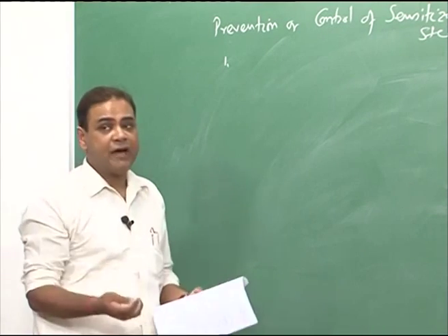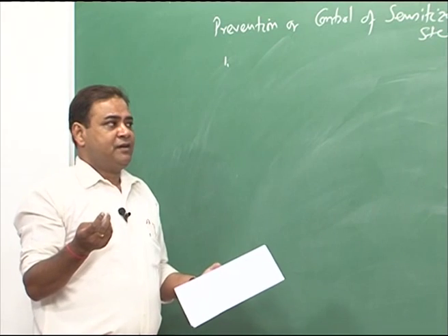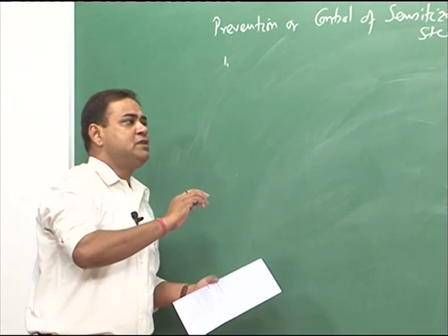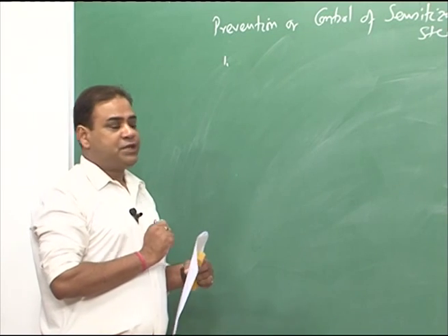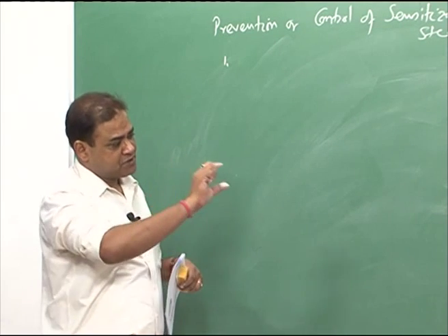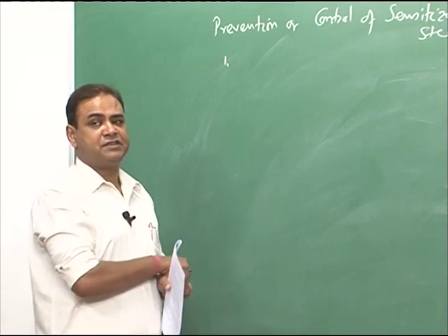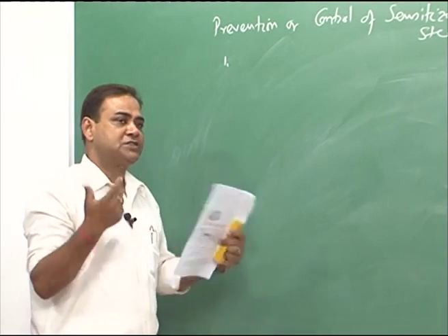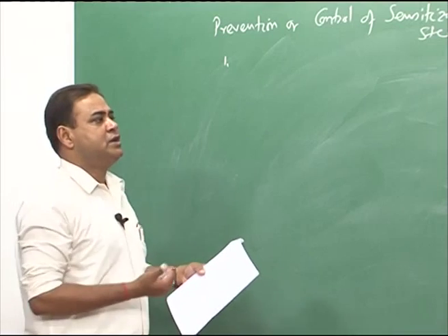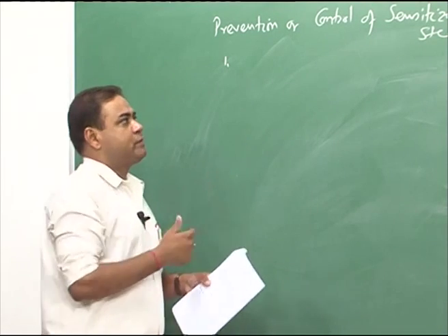And if we do not have sufficient carbon which can be left out by the austenitic lattice during cooling in the temperature zone of 600 to 800 degrees Celsius, chromium carbide cannot form, because there is not much carbon left for the chromium to take up and form chromium carbide.